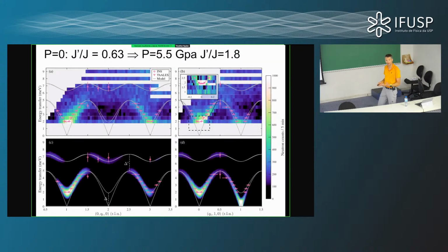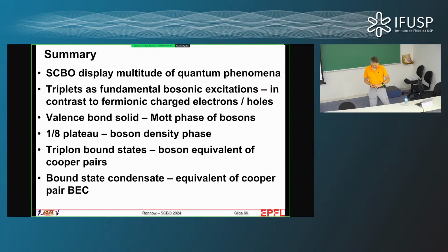So here's neutron scattering spectroscopy from a spin half system at 5.5 GPa. And the intensity shows that we have rather simple, well-behaved dispersive spin wave excitations, and Ellen, my postdoc, has been able to fit that. And so, to be very honest, there's nothing particularly quantum about this. We've basically taken this extreme quantum system and squeezed it into a semi-classical antiferromagnet with rather standard and well-behaved antiferromagnetic spin waves. Okay, so with that, I apologize for going slightly over time.